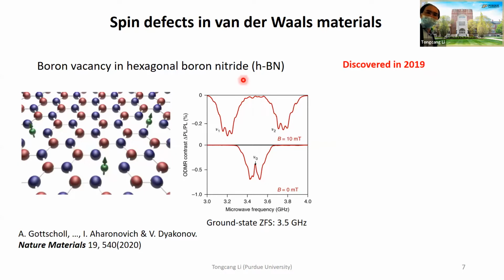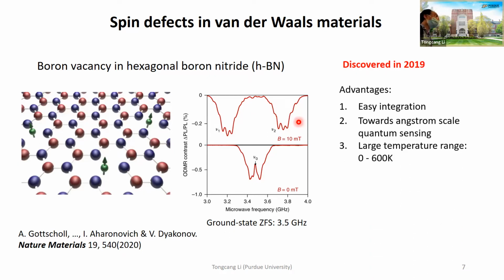Here shows the optically detected magnetic resonance of boron vacancy in 2 different magnetic fields, 0 millitesla and 10 millitesla. So you can see it's very different. That means you can also use this to measure the magnetic field. This one is at room temperature, 300 Kelvin.